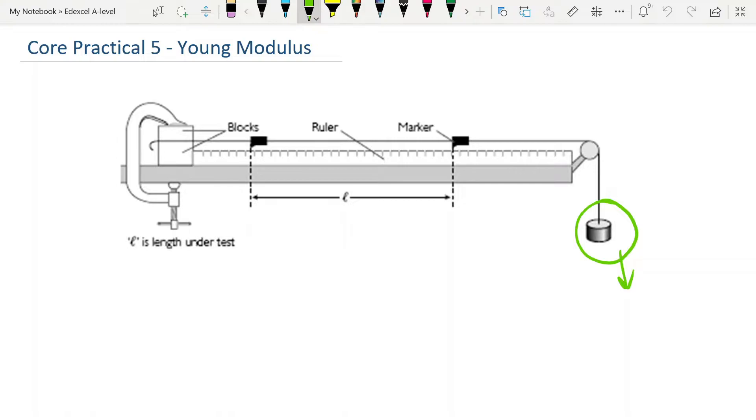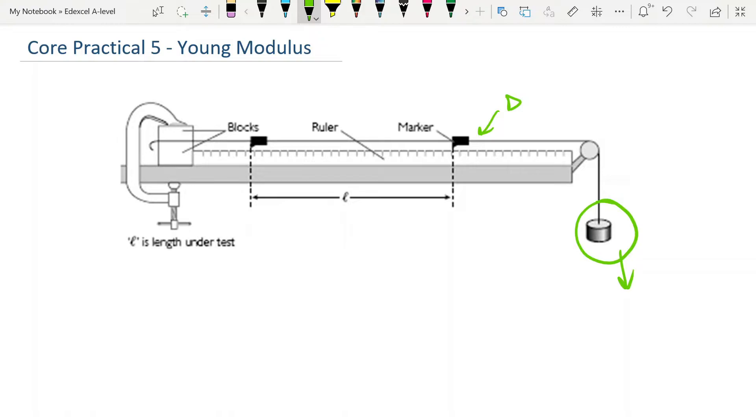The next thing you have to do is use a micrometer screw gauge to measure the diameter of the wire here. The best practice with this is to measure the diameter at five points along your wire and then turn your micrometer each time so you're measuring from a different orientation, just in case one edge of your wire is slightly flat. That way you're going to have five readings from which you can take an average and therefore have a better level of accuracy in the diameter of your wire.